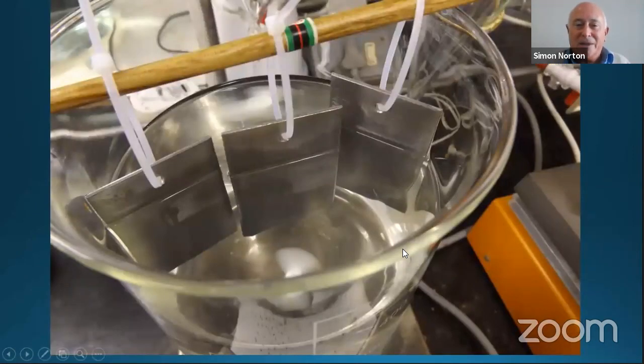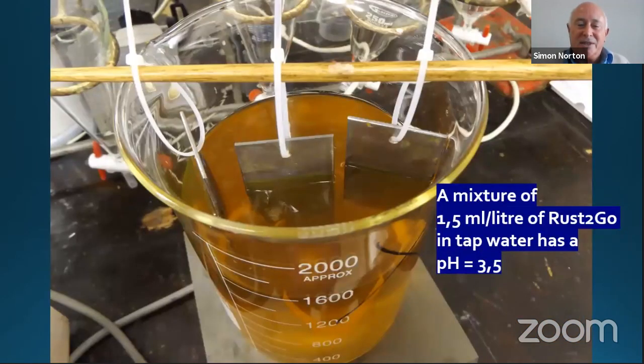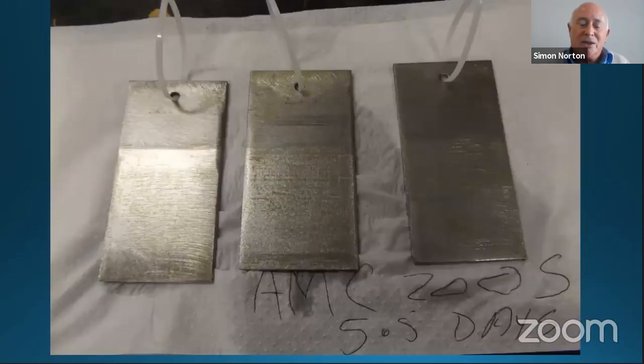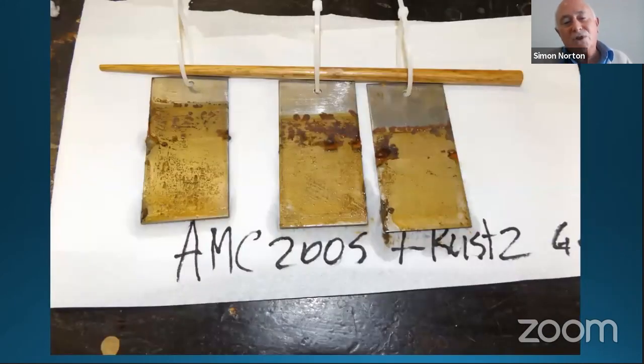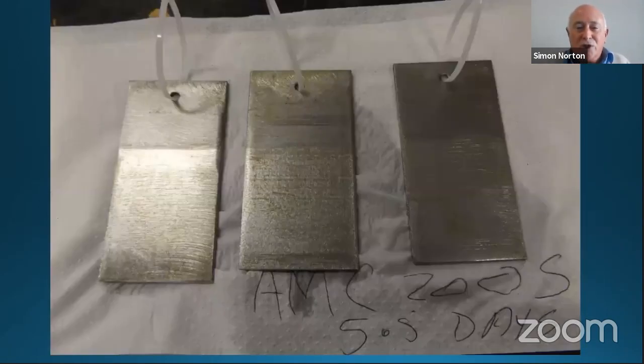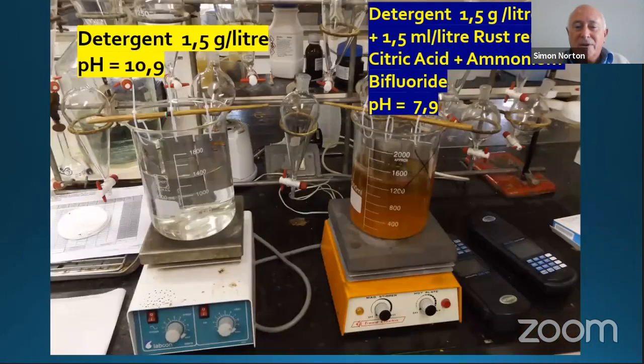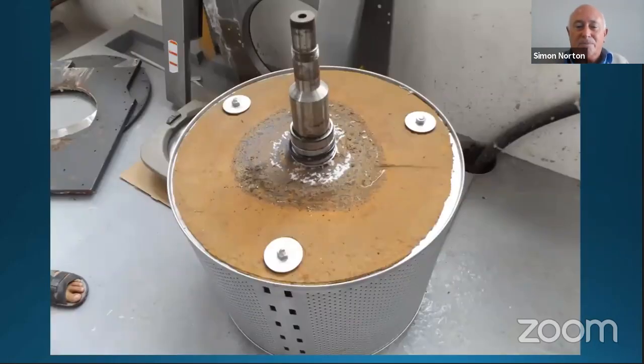And you can see the effect. That's what they looked like when they went into solution, the steel plate from the back, mild steel, beautiful condition. This is what the ones look like with the stain remover. The solution shows clearly corrosion. That's what a plate looked like just with detergent. This is what a plate looked like when you use the stain remover. So you can see that this particular stain remover attacked the carbon steel. It attacked the drum that I showed you early on. Go back a photograph here. It attacked this material here. It attacked this over here.